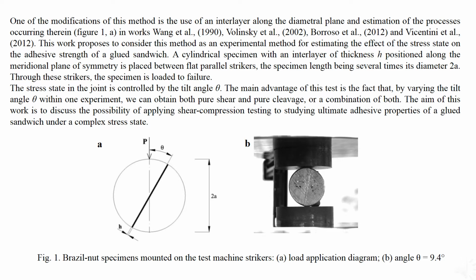A cylindrical specimen with an interlayer of thickness h positioned along the meridional plane of symmetry is placed between flat parallel strikers, the specimen length being several times its diameter. Through these strikers, the specimen is loaded to failure. The stress state in the joint is controlled by the tilt angle theta.